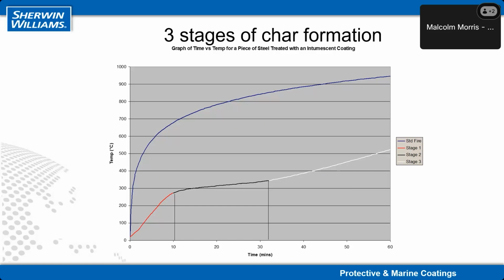Then after about half an hour, the char formation is complete. Your steel is encapsulated within the carbon blanket, and then it's just basically the insulating effect of the carbon blanket protecting the steel and insulating it for hopefully up to your 60-minute or 90-minute or 2-hour period.